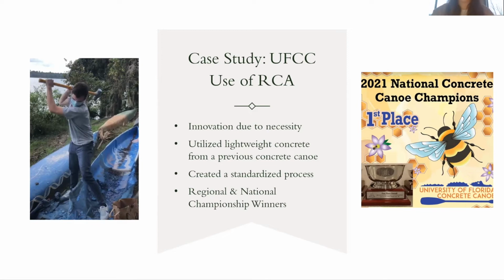In search of a lightweight yet durable replacement, we chose to create our own recycled concrete aggregate from one of our team's previous concrete canoes. After several failures at obtaining RCA, we finally developed a standardized method through which we were able to use RCA as a lightweight aggregate to great success.